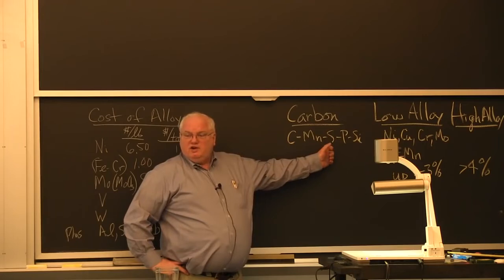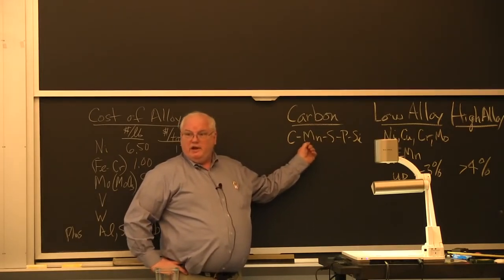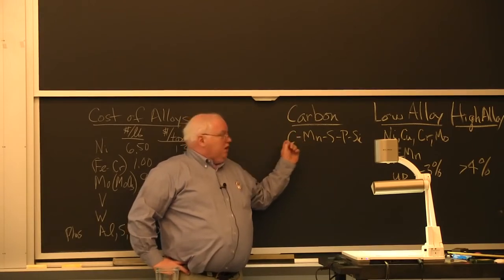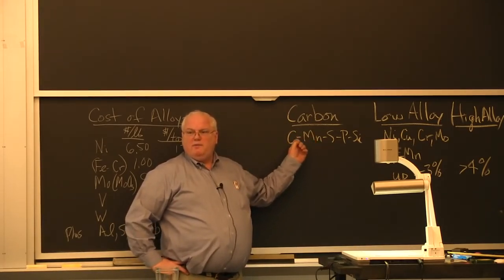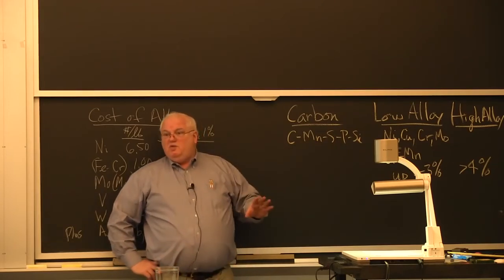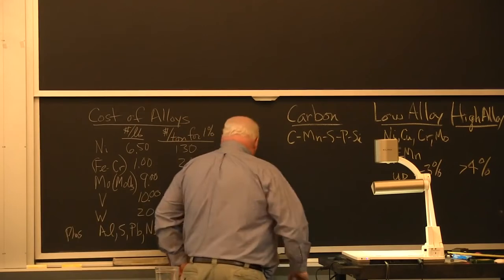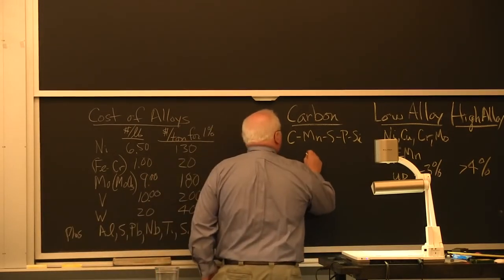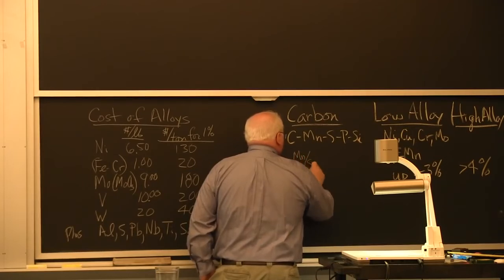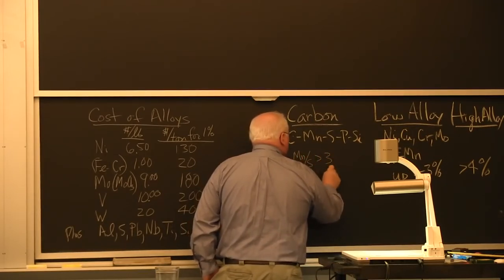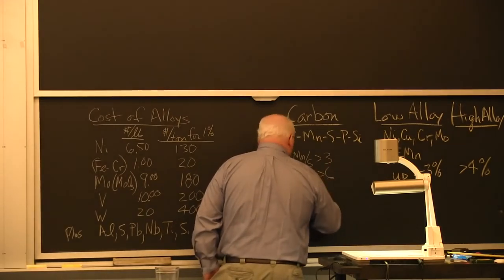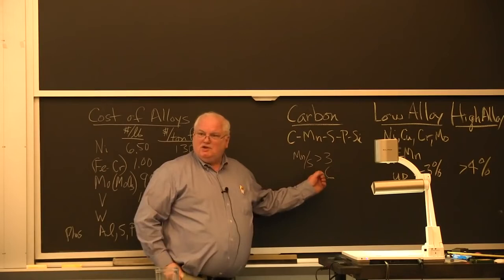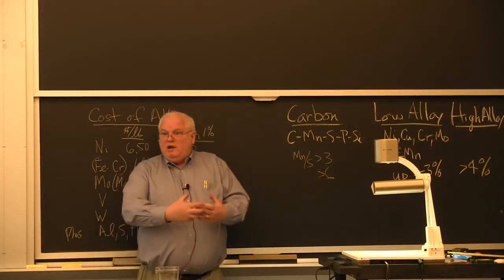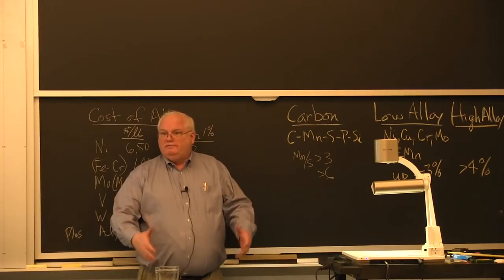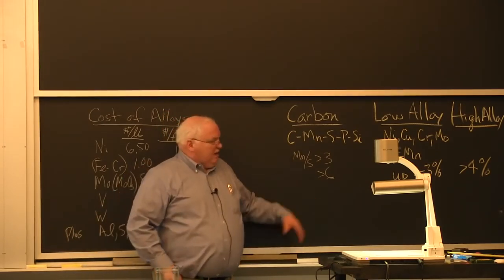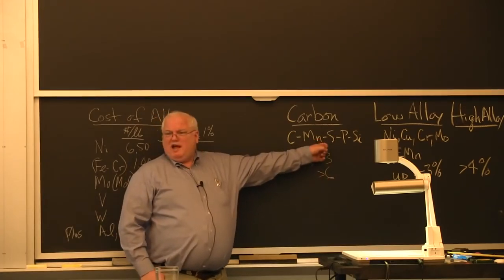So John Chipman came along and taught people, well, other people learned in the 1880s, you throw some manganese in. And I read one book, and they said the definition of steel is an alloy of carbon and manganese, because there is no steel that's made with zero manganese. In the old days, like before World War II, there would be a rule when you're welding that your manganese-sulfur ratio had to be greater than about 3 and preferably greater than 6. Okay? You had to have enough manganese so you didn't get this iron sulfide intermetallic in your weld metal and have the weld break in two as it cools down from cooling shrinkage stresses and stuff. We don't worry about that anymore. No one has sulfur that high anymore.